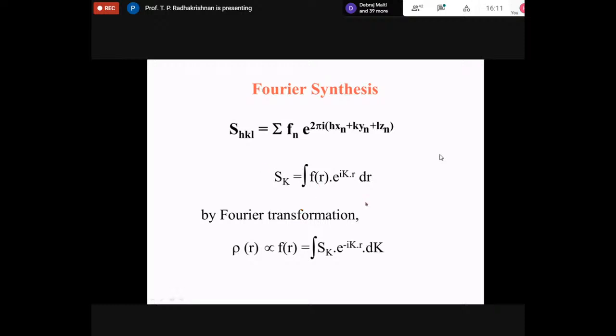So this is the very crucial step in crystallography. Essentially in crystallography, this is what you measure, the structure factor. Actually, you measure intensity converted into structure factor, and you integrate it to get the electron density. So this process converts the structure factor, which is information in this space defined by this vector k, called the reciprocal space. Those diffraction patterns which I showed you are basically a picture of the so-called reciprocal lattice. You convert that information into real lattice by this Fourier transformation, and what you get is an electron density map in real space. So r is a space coordinate in real space. Without that, you will not know.